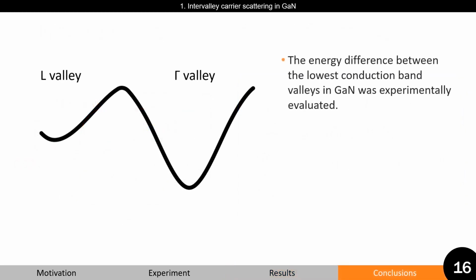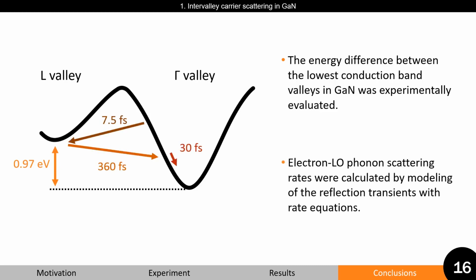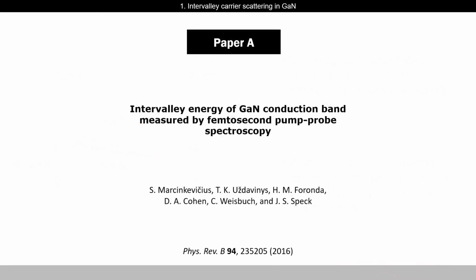This brings us to the first set of conclusions, first project. Energy difference between the lowest conduction band valleys was experimentally determined. In addition, electron longitudinal optical phonon scattering rates were evaluated by modeling reflection transients with rate equations. These results were published in paper A.